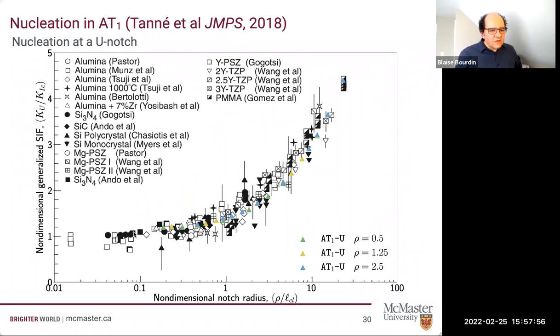And you see there's some kind of universal law that seems to happen. The black dots are the outcome of many of these experiments. The color dots are the result of phase field computation. And once again, no free parameter, but we still match the nucleation correctly. Okay, so I'll stop here. I focused too much on the success and not much on the challenge. The challenge is really to understand why this is working so well.